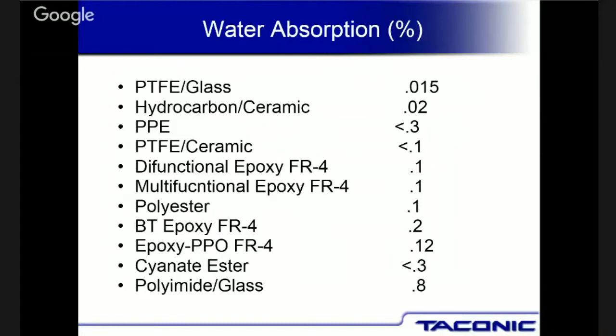But you look at, for example, where's polyimide on here? Polyimide glass, 0.8%, which is pretty high. That's a very high moisture content. So the board shop, or even you guys, when you're assembling these things, have to put these boards through a bake cycle to bake out any residual moisture that may be stuck in the board before you do other things to it, because you don't want the board to explode when you expose it to IR reflow, or in your situation where you're having high power running through these boards and they're getting really hot.